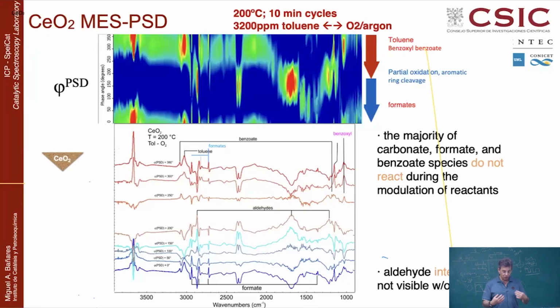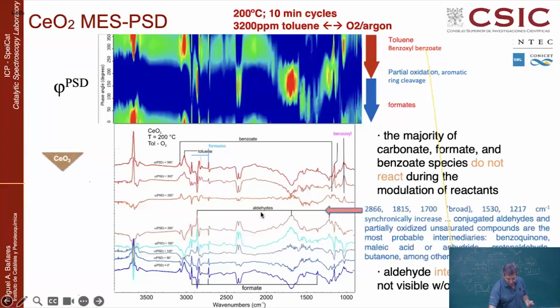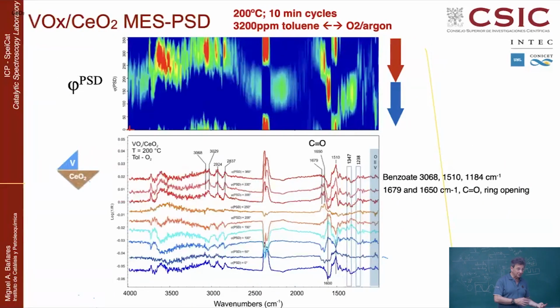And then you can analyze which one is growing and which one is decreasing. To us this was important because we couldn't see what the key intermediate was going from the toluene to the CO2. And then we saw things that were absolutely not apparent in the spectra, infrared or Raman. The presence of aldehydes was not apparent. We saw a lot of bands that increase synchronously at this moment. Basically, they were conjugated aldehydes, partially oxidized, unsaturated compounds, crotonaldehyde, probably maleic anhydride, butanone, many compounds associated with the combustion that you can see now and before were totally covered because of much stronger bands of spectators.